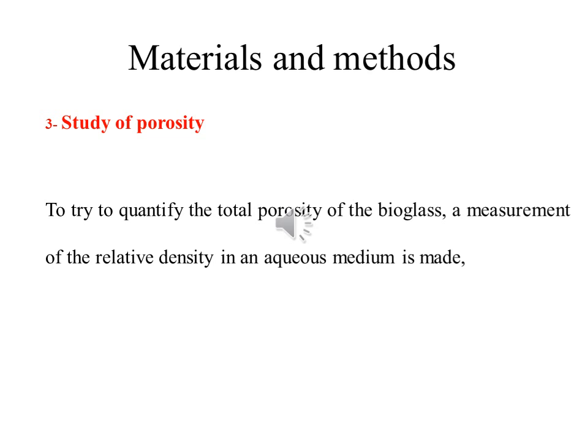Study of porosity for these glasses: to try to quantify the total porosity of the bioglass, a measurement of the relative density in an aqueous medium is made. The porosity is very important. This glass must be more than 50% for porosity.